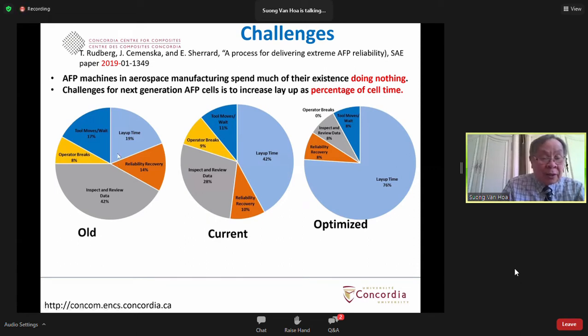Now, the reason they say that is because they analyzed the different kinds of time and motion that I mentioned to you in the previous slide. And they find that in the previous way, the layup time, that means the real production time, the time when the machine lays down the material, only accounts for 19% of the total time when the machine goes into a production cell. So what happened to the other time? The inspect and review is 42% of the time. Inspect and review means what they did before is that they have to do that manually. That means they have to get an operator to go and look at every part. So it becomes very fast to deposit, but it takes a long time to inspect. So that is not very good.